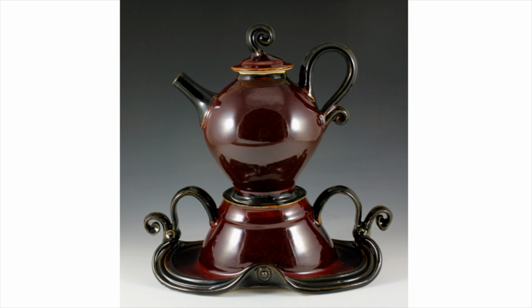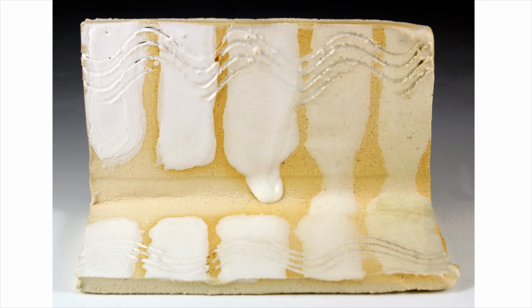Now there are several ways to lower or raise the melting temperature and control the flow of a glossy glaze. One is to take out all of the flux and add it back in 10% increments. Note how the flux ingredients take the glaze from very stiff and dry to eventually a runny, glossy glaze.